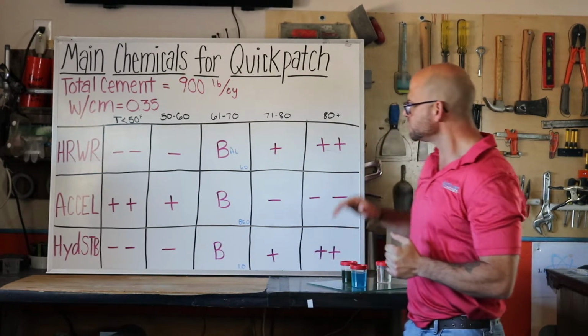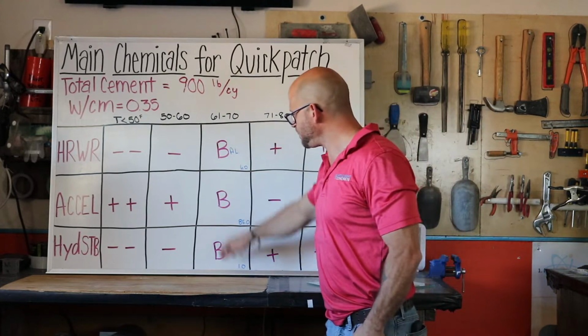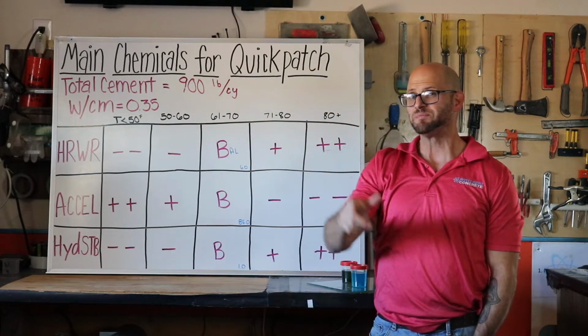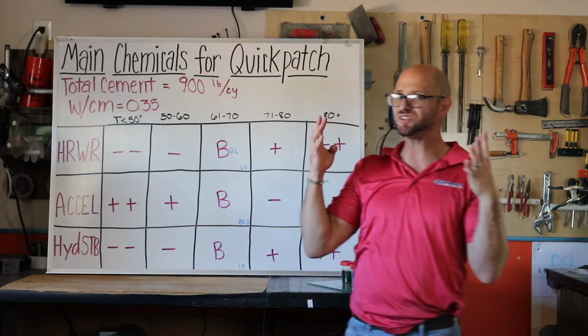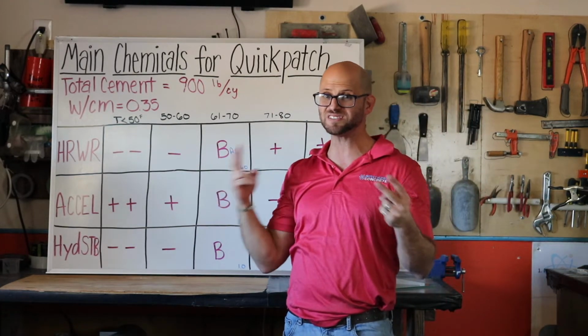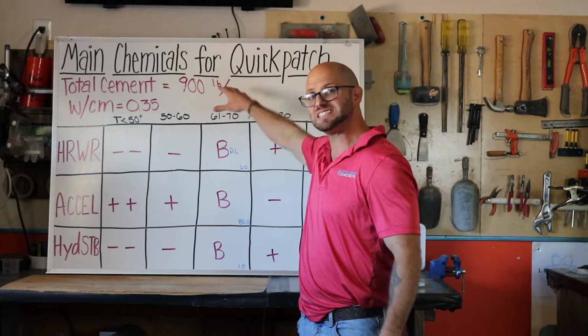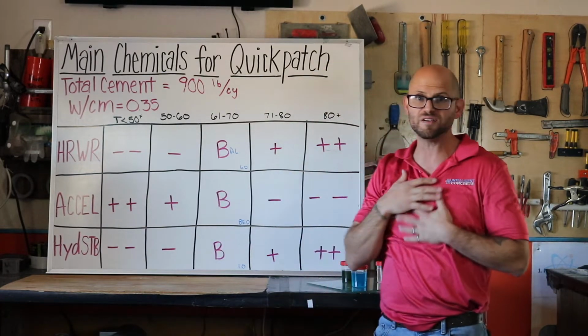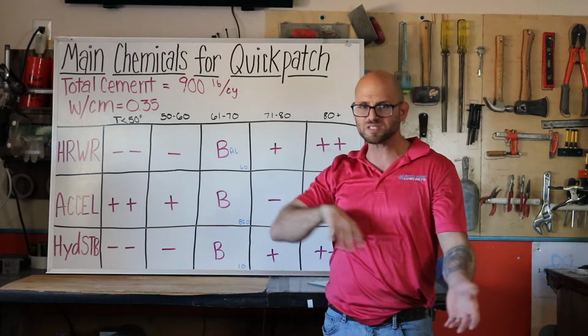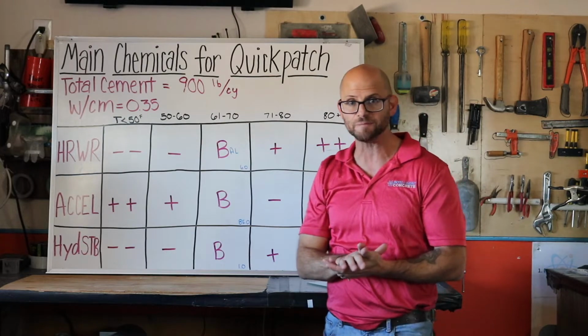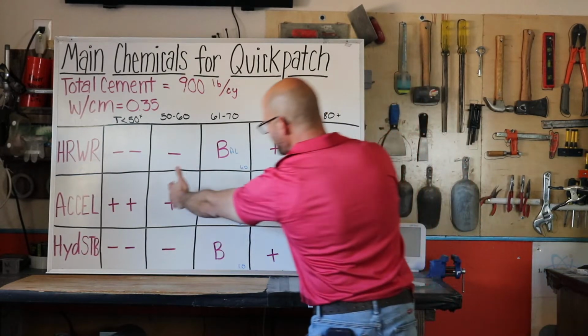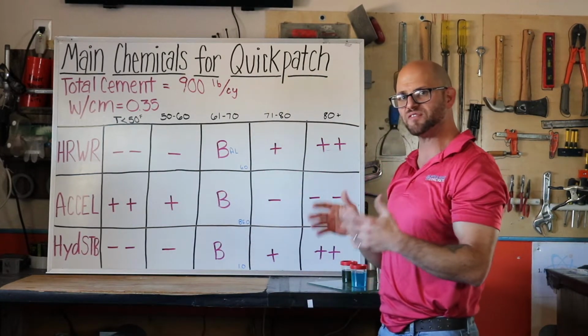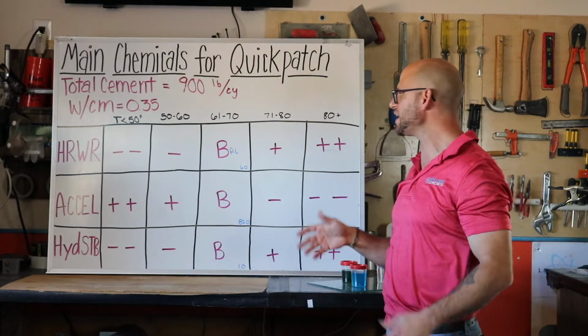Okay, so looking at this chart right here, I have my balanced condition. Now I told you I designed one mix, but it's actually 4 mixes, or 2 mixes on either side of that stable temperature. And where we live, that stable temperature is around 61 to 70 degrees Fahrenheit. So now what I'm doing is I'm taking either side of that temperature by 10 degree increments.